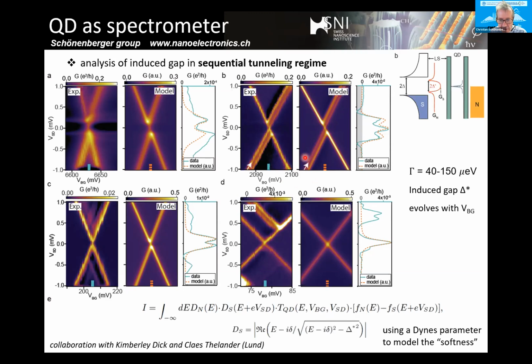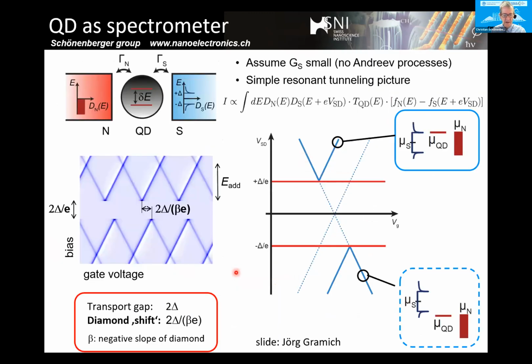Now, if you have never seen this, I should maybe show you this plot quickly. So assume you have an NS junction with a quantum dot, and let's assume only quasi-particle tunneling is possible. We have a very good gap. Then what will happen is that instead of the Coulomb blockade diamonds touching at zero bias, they will be shifted away by plus minus delta, and this is what you would expect to see. So this is the blue part. This would be the onset of quasi-particle tunneling in this region, and this in this region here. And in dI/dV, you would see these lines.